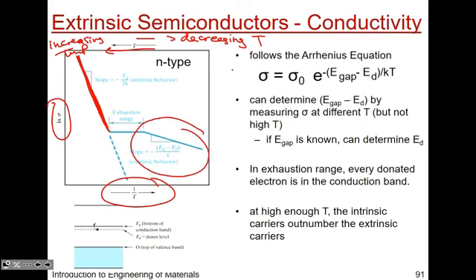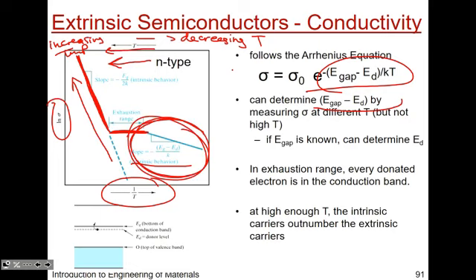At lower temperature, the conductivity is dominated by the charge carriers from your dopant. So we call that extrinsic behavior. And the slope of that is defined as your band gap minus the energy of your donor state, divided by k. There's this interesting region here where you've excited all the electrons from, let's say, your phosphorus in silicon. At some point, there's an exhaustion range, and then as you increase the temperature some more, the dominating part of your conductivity lies in the excitation of your intrinsic carrier concentration. So what that means is if you dope phosphorus into silicon, at lower temperatures, the charge carriers from phosphorus are what's being excited, and then at higher temperature, it's more intrinsic behavior.